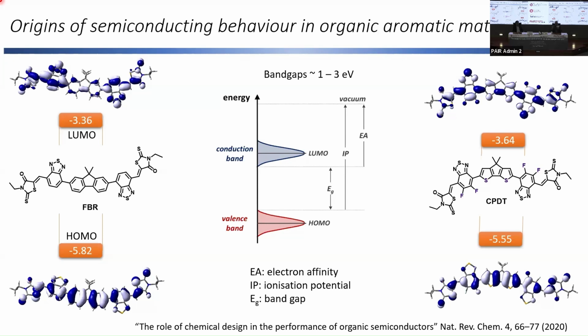In polymers, poly-3-hexylthiophene does suffer from grain boundary effects. On the other hand, the most crystalline polymers here are maybe 30% crystalline at maximum. The rest is pretty amorphous. I mean, that's the same with just about any polymer, unless it's monodisperse and really carefully processed. Generally, you have a lot of disorder, which means that the effect of grain boundaries in polymers is much less than in small molecules.